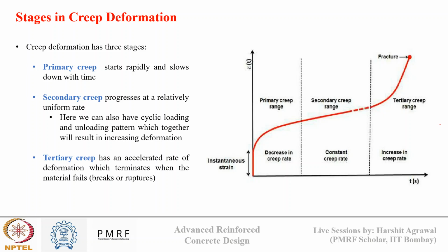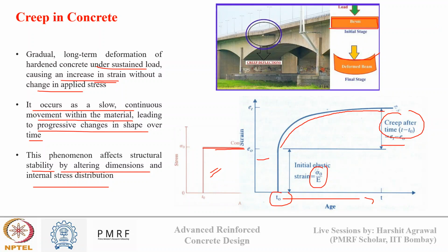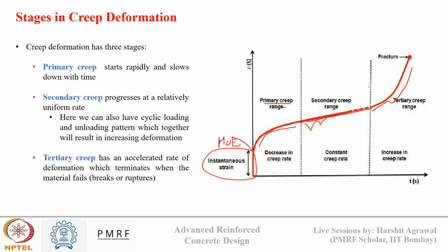Generally, deformation due to creep is divided into three stages. Initially, when the load is applied, there is instantaneous strain that is due to the modulus of elasticity. Then the primary creep occurs, which starts rapidly and then slows down. Then there is secondary creep, where it is almost constant, increasing at a uniform rate. Here we can have cyclic loading cycles also. And then there is tertiary creep, where there is accelerated deformation before material failure. So in this pattern from the initial stage to the final stage, initially the creep rate is strong, then it becomes linear, and then it takes a sudden growth as cracks form, grow, connect and propagate uncontrollably.